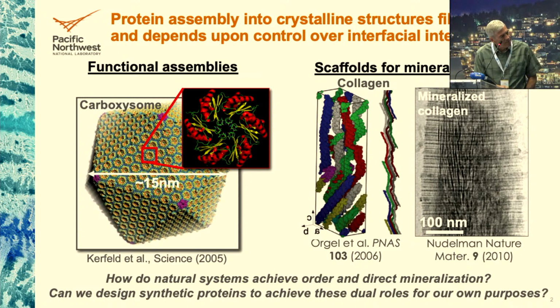And then you can see in this TEM micrograph from Nico Sommerdijk's group where the mineral components diffuse in through these certain bands. The banding structure here is because the electron density is different in different places where the amino acid residues overlap, and so this is a very characteristic pattern of the organized collagen. The vertical dark lines are actually the platelets of hydroxyapatite, calcium phosphate, that form in this matrix. So this highly organized matrix produces a highly organized, very hard material that has great mechanical properties, despite the fact that collagen on its own is quite a weak and not very useful material. And the mineral platelets are little nanoplatelets that have very little strength on their own.